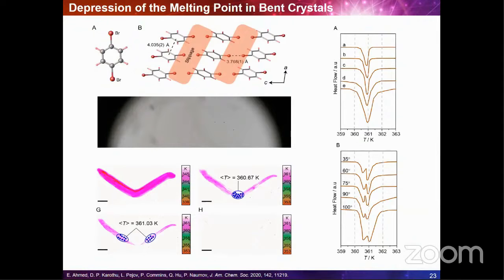So these thermomechanical effects become more pronounced with heavily damaged crystals due to obviously increased concentration of defects, and ultimately they result in a large temperature spread of the associated phase change, in addition to some melting point depression in the form of damaged crystals relative to their pristine counterparts. The mechanical treatment during sample preparation has a profound effect on the melting of a pure substance, and this result could be critically important where you need to determine the exact melting point, for example, for purpose of structural identification, polymorph identification, or purity check.